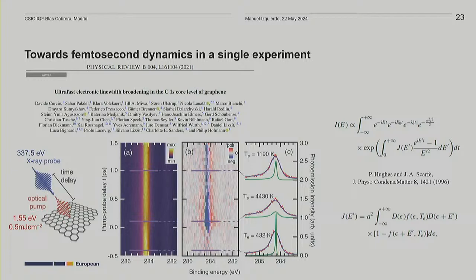I'm going to focus in the next on two examples. One is the study of the ultrafast electronic linewidth in graphene, and this follows a proposal from the 60s that basically proposed what would happen to a core level when you do a very high excitation, and how high could the electronic temperature of the system go by keeping the material still intact. So these colleagues, they did an experiment. They excited graphene with 1.55 electron volts, so basically around 800 nanometers, and this fluence 0.5 millijoule per square centimeter.